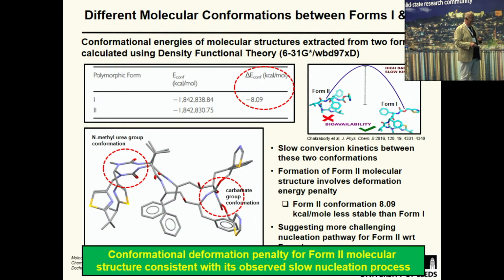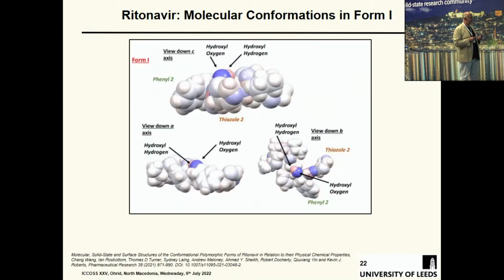So the conformational deformation penalty for form 2 molecular structure is consistent with its observation of a slow nucleation process. And the whole thing about ritonavir is it's not magical, it's just that the form 2 primary nucleation is very slow indeed. And there are plenty of very slow primary nucleation processes. But once you form it, secondary nucleation takes over and you can routinely get it.